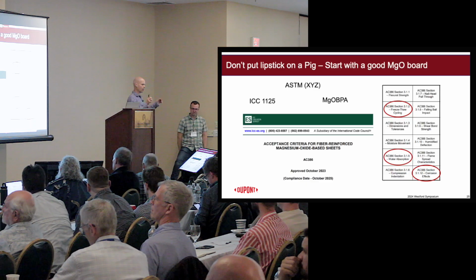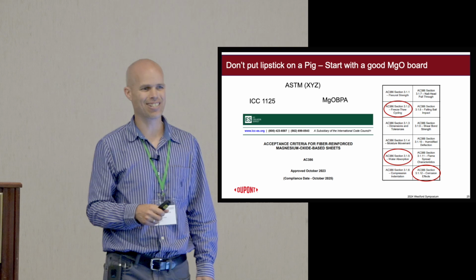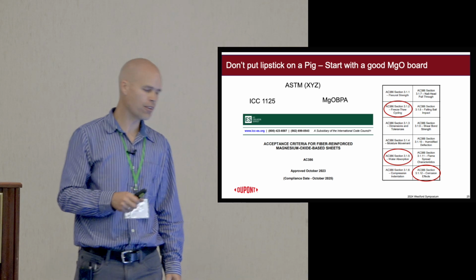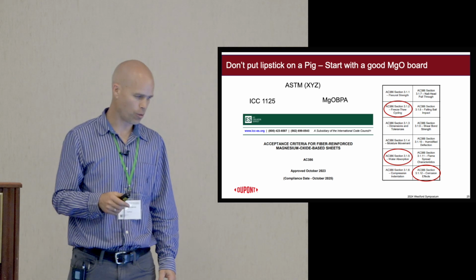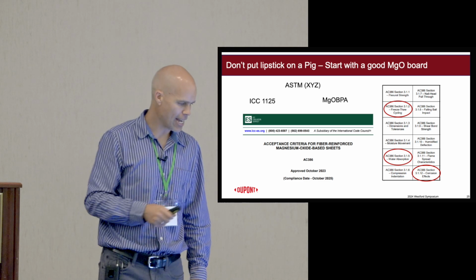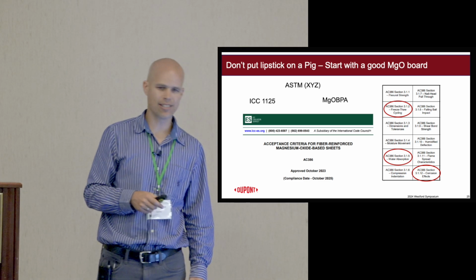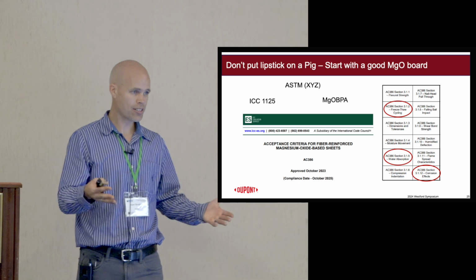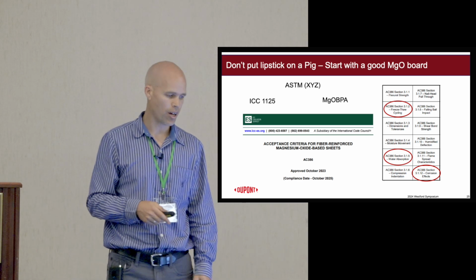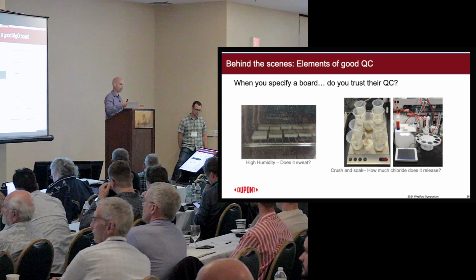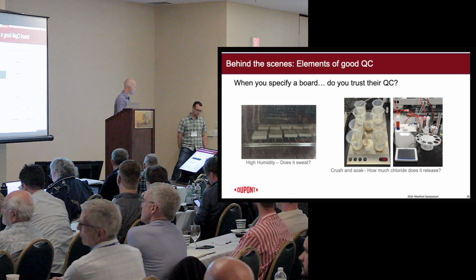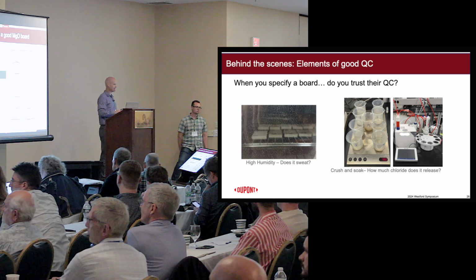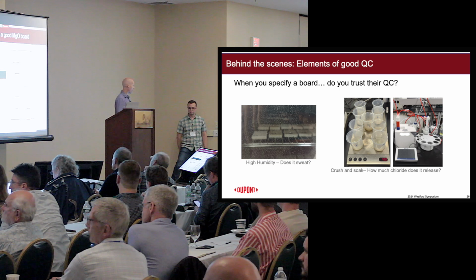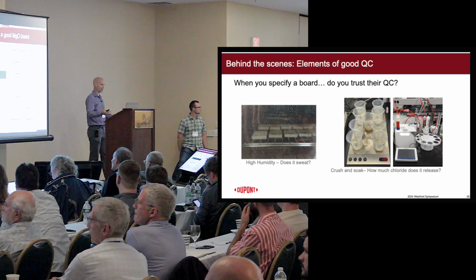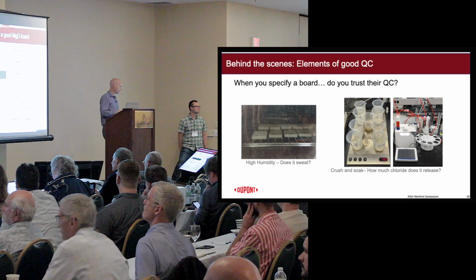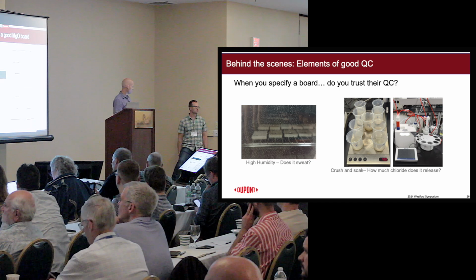There are some standards that are coming out at ASTM XYZ because that standard is still being written. But there are organizations and groups that are involved in creating those. The AC386 from ICC-ES, that is in place, and people are testing and showing compliance and being able to make really good boards. You can see in the requirements for that, freeze-thaw cycling, the ability to maintain structure as it gets wet and dry, water absorption, how well does it absorb water, which is related to how much chloride is around, and then also corrosion and corrosive effects.